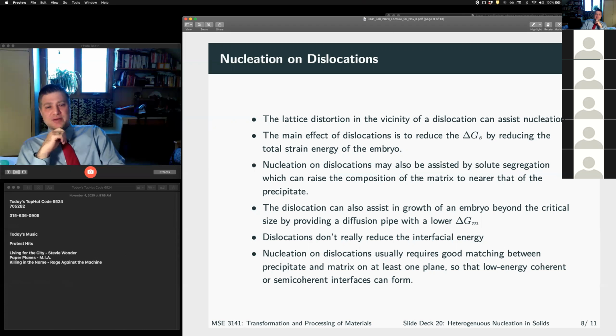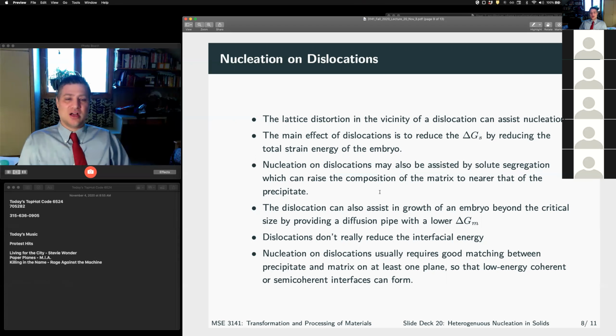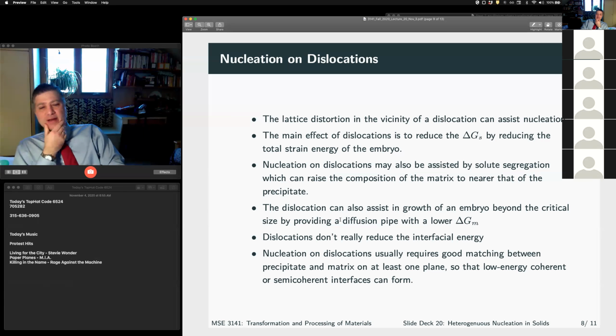We can also reduce the energy because diffusion is faster along the dislocation. We have pipe diffusion, right? So by nucleating at a dislocation, we can get a bonus from our delta G of migration, okay? So dislocations don't really reduce the interfacial energy, but we get a boost from solute transport being easier and the strain effect, right? So generally what we see is secondary phases that nucleate on dislocations usually are those that would normally nucleate homogeneously, but they're going to nucleate much faster at the dislocation, right?